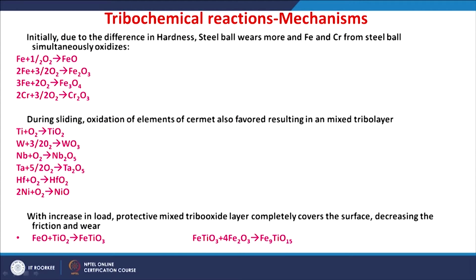Generally what happens in the initial stages of sliding is that, due to the difference in hardness between the steel ball and the cermet, which has higher hardness than the steel ball, the steel ball wears out easily, and then the elements from the ball, iron and chromium, get oxidized, because all these tests were done in ambient conditions. So, there is a chance that iron oxides or chromium oxides will form. As the sliding continues, these hard debris of iron oxide or chromium oxide will abrade the cermet material as well. So, we saw some signatures of the abrasion and the entrapment of this debris. This abrasion leads to removal of material from the cermet surface.